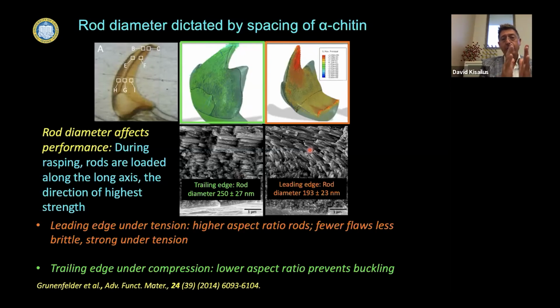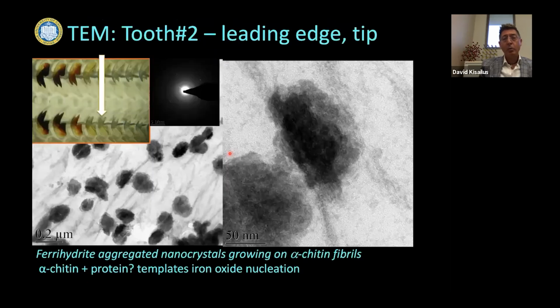Those alpha chitin scaffolds are actually spaced a very specific distance apart that yield specific diameter rods on the leading edge, more narrow, that provide some tensile strength. On the trailing edge, where the tooth might undergo some compressive forces, they are larger in diameter, which might prevent some buckling that occurs. So those alpha chitin fibers are present in these teeth, and every time that we see a mineralized particle, it's always attached to an alpha chitin fibril. And again, it's likely in most mineralized systems, you have proteins that are co-associated with these chitin fibrils. These are nucleation sites, and it's a heterogeneous nucleation process.